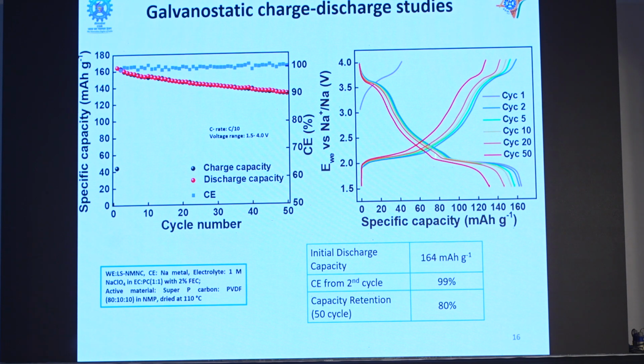And this is called a voltage profile. In a voltage profile, we plot the specific capacity versus voltage. It can be correlated with the cyclic voltammetry you have seen before. So initially we see there is a plateau around 3.5 volt. This plateau is nothing but the reaction of nickel and cobalt.